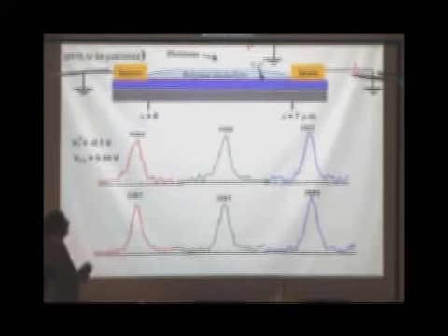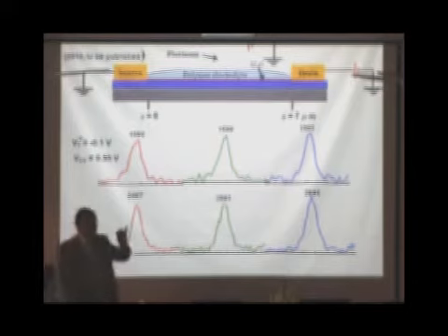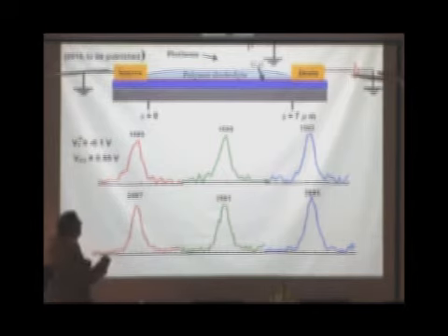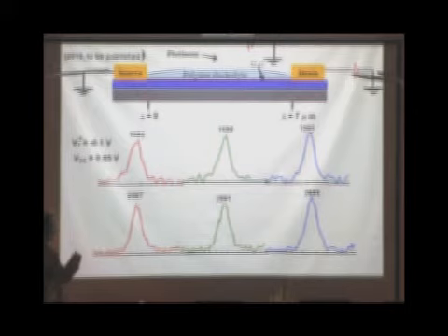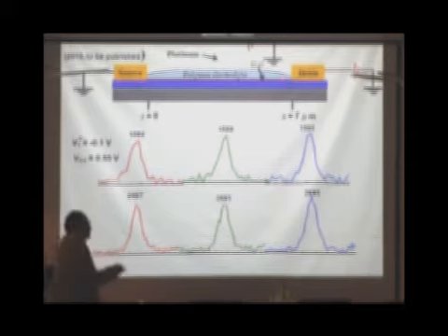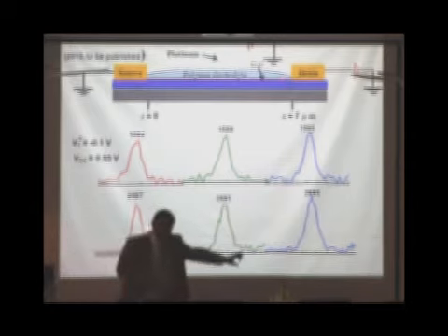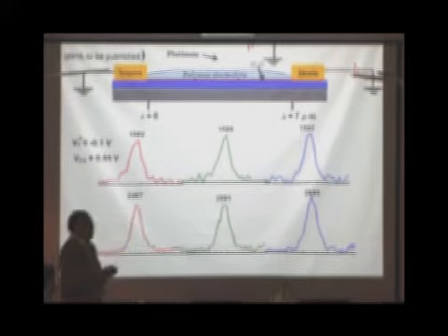And how do we confirm? Again, you do Raman scattering as a function of distance. So this is micro Raman, so your spatial resolution is high. You do Raman scattering when the device is working, along the length. Look at this. If you do Raman scattering at this point, the frequency is 1582. Same device, same condition, you do it here, it is 1593. And quantitative analysis tells you what is the profile of the carrier in this layer. So this is something again you can do quantitatively.